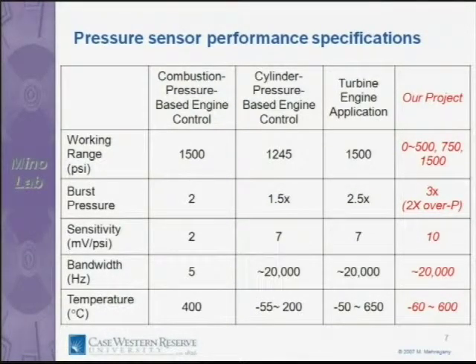And what Li Chen did was essentially do a mask design for pressure sensors up to 1500 PSI. These devices have to withstand large overpressure, usually a factor of 3. Reasonable sensitivity up to 20 kilohertz of bandwidth and temperature up to 600 degrees C.